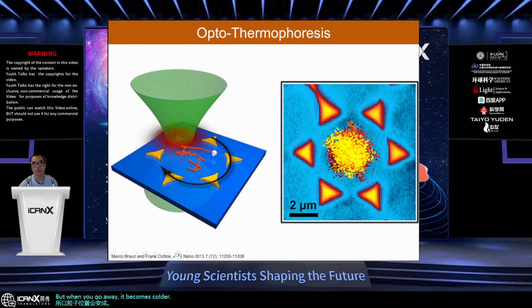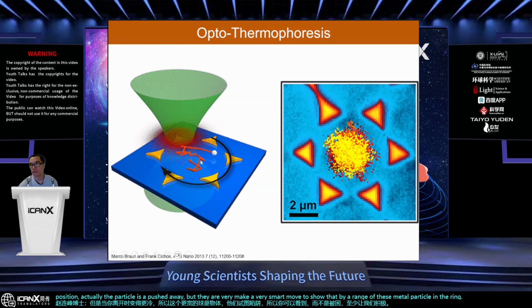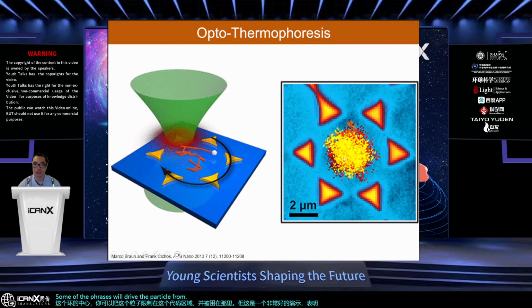So this white ball is the object they are trying to trap. You can see that instead of being trapped at the laser beam position, the particle is actually pushed away. But they made a very smart move by arranging these metal particles in a ring configuration, so you can define a cold region in the center of this ring, and you can confine the particle in this cold region and have it trapped there. This is a very nice demonstration that thermophoresis will drive the particle from hot to cold regions, but it is not good enough to achieve dynamic manipulation of these particles. Here is just the static confinement.